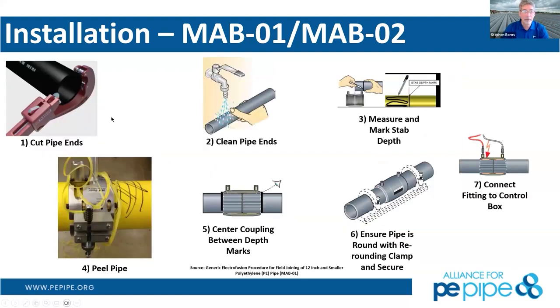Very quickly, these are the steps. Cut the pipe ends. Clean the pipe ends. Can't stress this one enough. This is the first cleaning step. Mark the stab depth of your pipes. How deep does it need to go into that coupler? Then you're going to scrape or peel the surface off. That's going to give you a nice clean surface that the electrofusion coupling is going to bond to. And this is a very key part of that. Then you're going to make sure that when you stab it to the mark depth, that you're going deep enough to get full stab of those couplings on both sides.